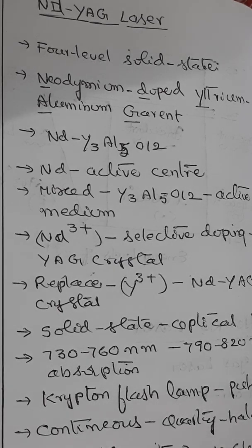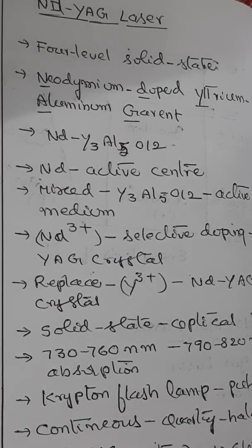Now here is one more point you have to understand, which is not part of your syllabus. The amount of neodymium dopant in the material varies between 0.5 and 1.5 molar. Higher dopant concentration is used for pulsed lasers and lower concentration is suitable for continuous wave lasers. Nd:YAG is pinkish purple in color, with lightly doped rods being less intensely colored, almost whiter than heavier doped ones. Now how does pumping take place here?